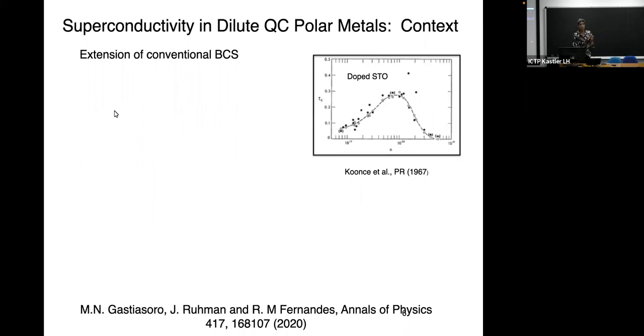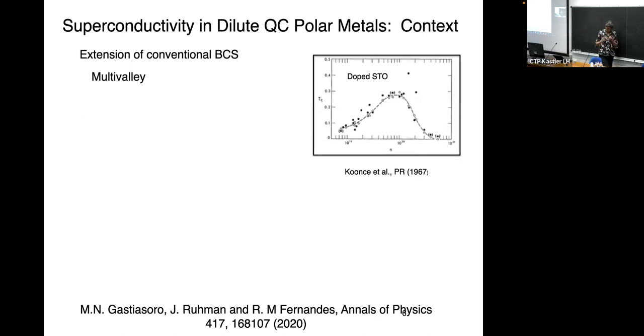Well, one of the problems with doping, dilute, is the fact that the Coulomb repulsion will be very strong, okay? The Coulomb repulsion will be long range, which is a Q equals zero instability. So what Marvin thought about was, wait a minute, I know a lot about semiconductors. In particular, he had done quite a bit of work on gallium arsenide. Gallium arsenide is a multi-valley semiconductor. Okay. So what Marvin suggested was, let's consider superconductivity, but not in the usual case, but by invoking large wave vectors from valley to valley. And if you do that, then you can somehow get around the Coulomb interaction.